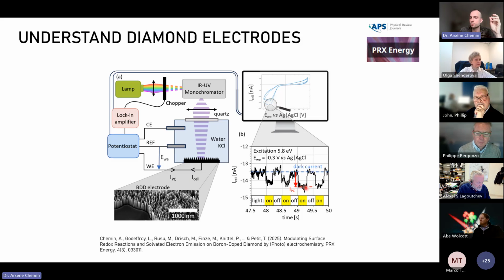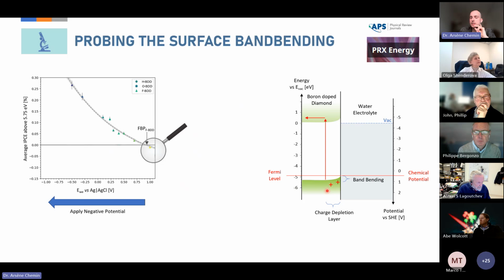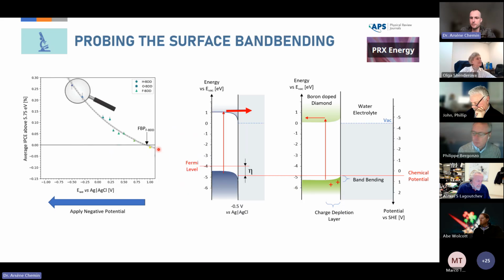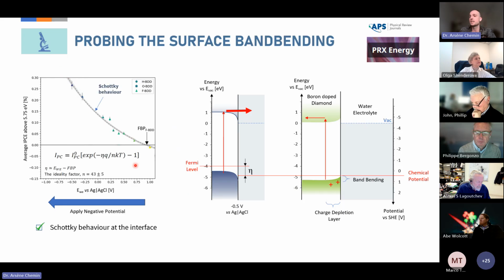And we can use this light in order to probe the diamond interface and band bending. So for instance, if we excite the diamond above the bandgap and there is an upward band bending, the electrons will go to the inside of the diamond electrode, and that will give a negative photocurrent, as you can see here. But if we start to apply a potential, we raise the Fermi level in the diamond electrode, and that will change the direction of the band bending. Then when we photoexcite the diamond, this time the electrons will go in the liquid, leading to a positive photocurrent here. And we can do that for many different potentials, and we get this kind of curve here that you might recognize as being a Schottky diode.